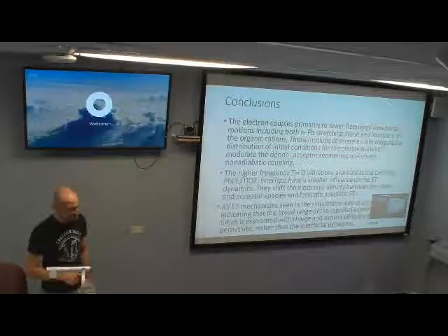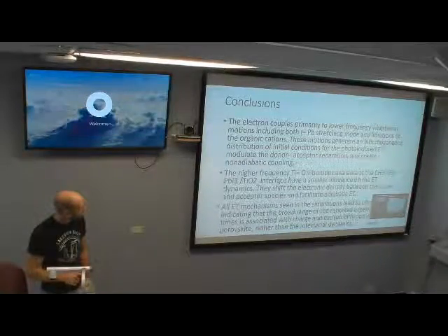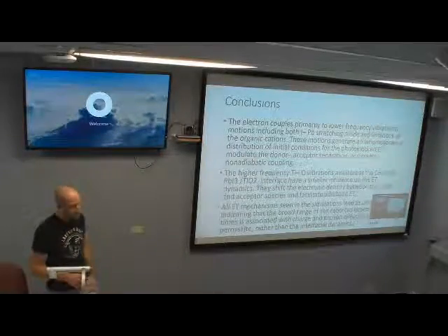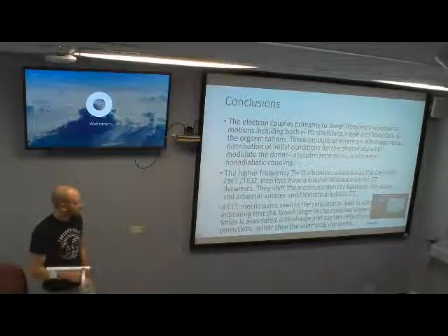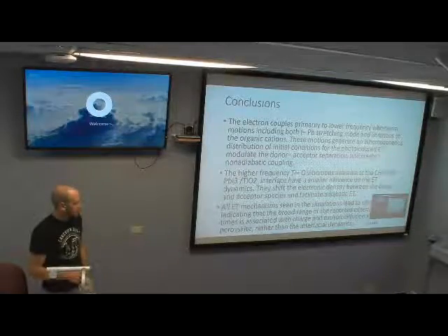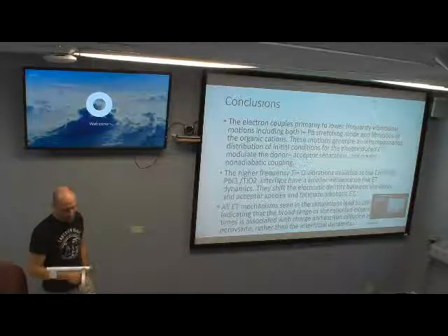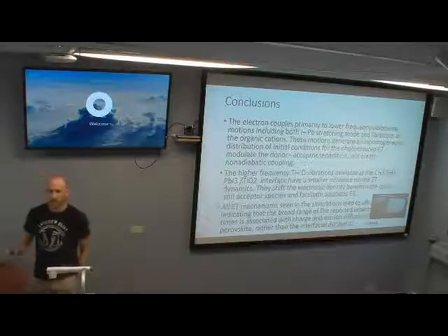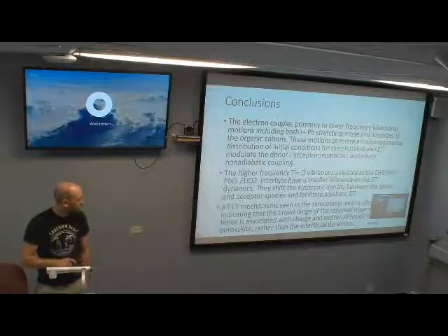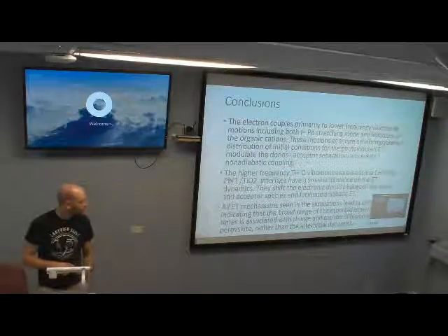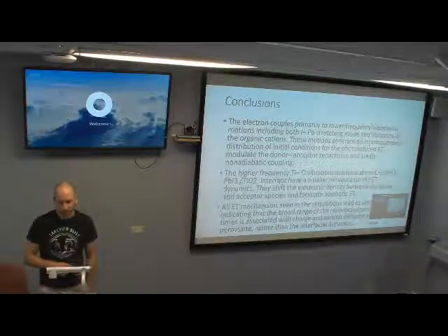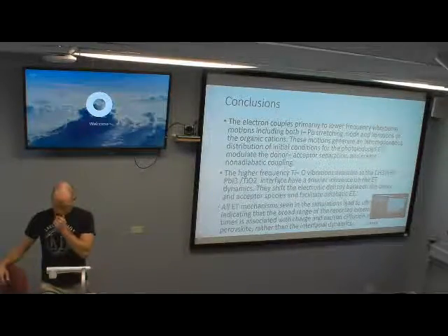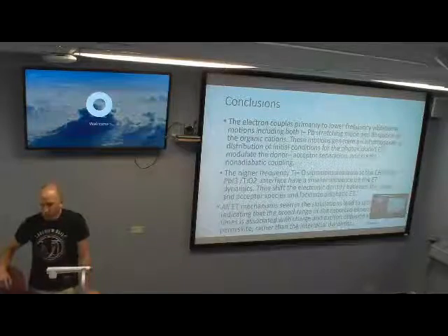But what about this iodine-lead? Does it contribute? It says the electron couples primarily to the low-frequency vibration of the iodine-lead structure. So these are more so how it ends up relaxing down, and create non-adiabatic coupling. So it's really the iodine-lead contribution that is main for non-adiabatic coupling, according to this one.